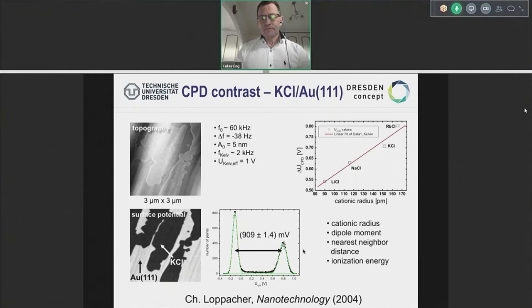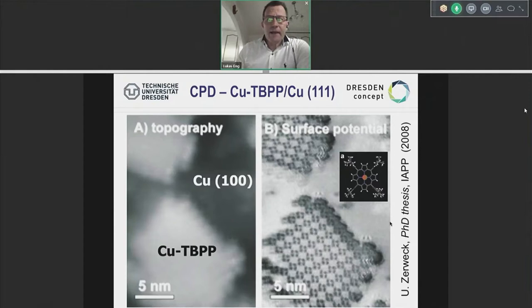We've done such an experiment by changing the cationic radius now, not only using potassium chloride, but going through all these halides, as you see here. And you can also see they go fantastically in line with the cationic radius and the surface potential. Or in other words, the chemistry is really linked to the cation radius. It's a clear connection. That means actually this gives us a lookup table in order to differentiate in a mixed system who is who.